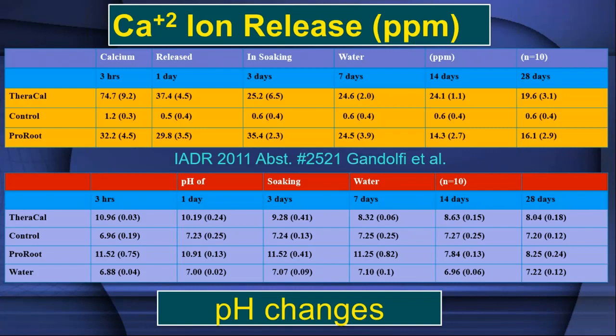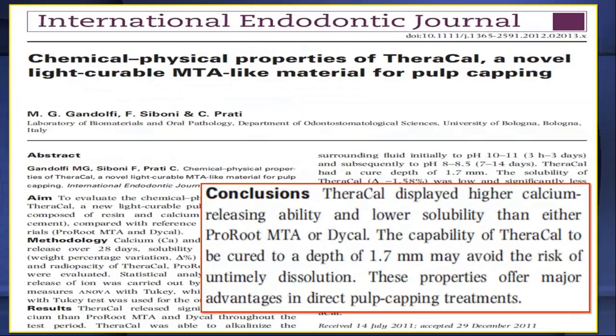Same thing for the pH. If you look at the pH of it, ProRoot's a little bit more alkaline at 3 hours, about the same at 1 day. It's a little bit more at 3 days, a little bit more again at 7 days, but at 14 days, TheraCal is more alkaline. So it kind of all works out. And one of the big early thought processes was that it's evening out these slopes. It's flattening the curve. So it must be good, right? When you flatten the curve, it must be good.